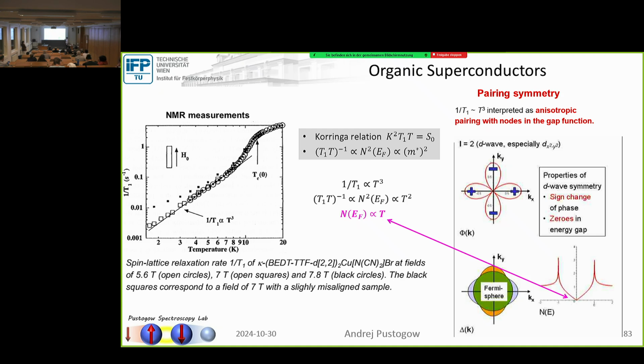And this is indicating the size of the superconducting gap. If you have a Fermi surface here, then you form a gap, so you don't have a Fermi surface anymore. And the size is largest along the x or the y direction. But if you go from the x towards the y direction, when you go from minus to plus, you must cross 0 at some point, because the phase is different, and this means that your superconducting gap must have a node.